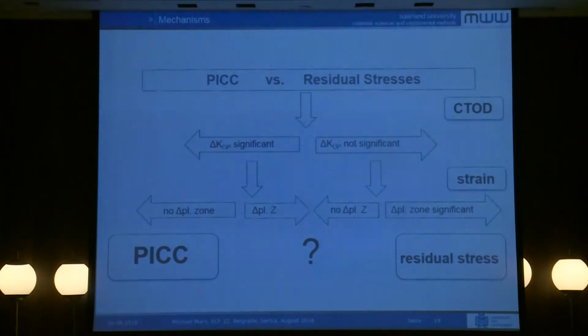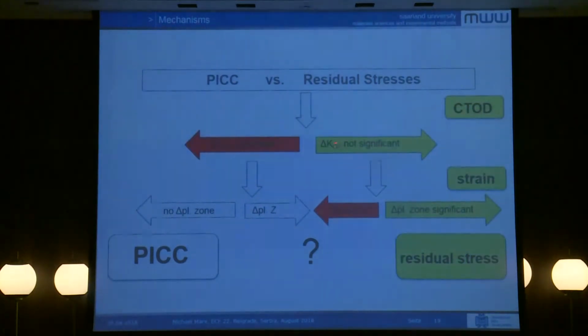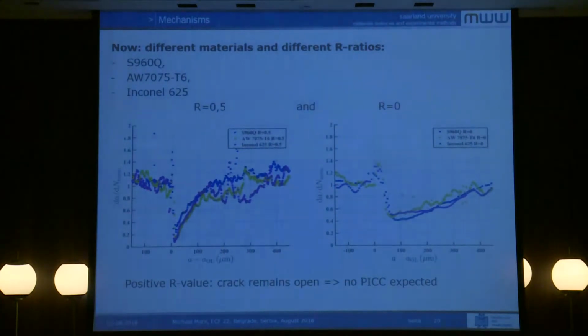So what we think is working is, if you have a look here, we would expect plasticity-induced crack closure or residual stresses. We find that we do not have an influence on the opening delta K, but we have a strong influence on the maximum delta K and a strong influence on the plastic zone, and therefore we think it's our residual stresses that are working here for the retardation, and then it takes some time until plasticity-induced crack closure comes into account again.